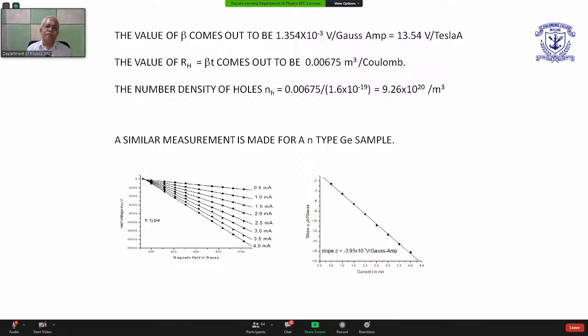From this, we get the number density of holes, because we see that RH is inversely proportional to the number density. So using the value of RH and the thickness, we can get NH. It turns out that NH is something like 9.26 times 10 to the power of 20 per meter cube. Once I know NH, then I can, of course, determine the value for the mobility.